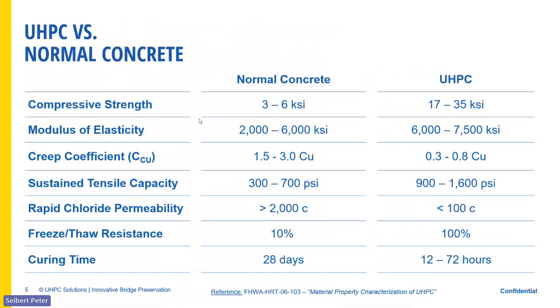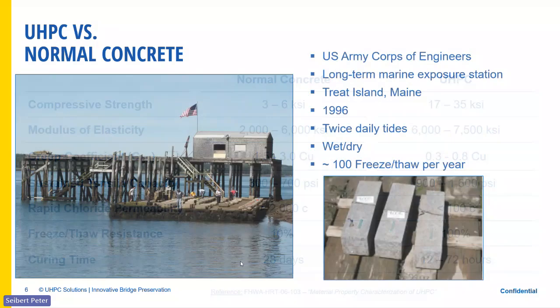Just generally, if you compare UHPC with regular concrete, you can get very high compressive strength, 17 to 35,000 PSI. 35, you do thermal treatment with that. Generally speaking, the cast in place materials are in the ranges of 17 to 25 KSI. Again, you can sustain tensile strength. You have a very dense material. Most of them have, in the rapid chloride test, less than 100, generally in the 15 to 20 Coulomb range, and it's resistant to freeze thaw.